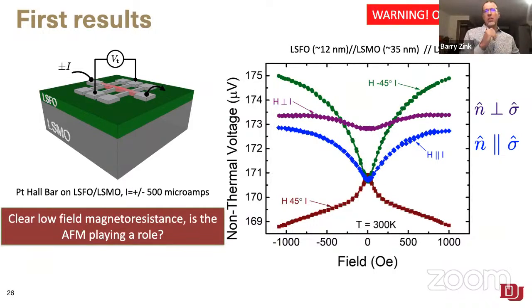But it seems that the zeroth-order statement is that the spin Seebeck parts may be kind of boring, but the electrically driven effects are showing some very interesting dependencies on magnetic field. So here, this is rotating the field in the plane and measuring that transverse voltage. This is platinum on top of this LSMO layer, and you can see these pretty significant, very easily measurable magnetoresistance changes.